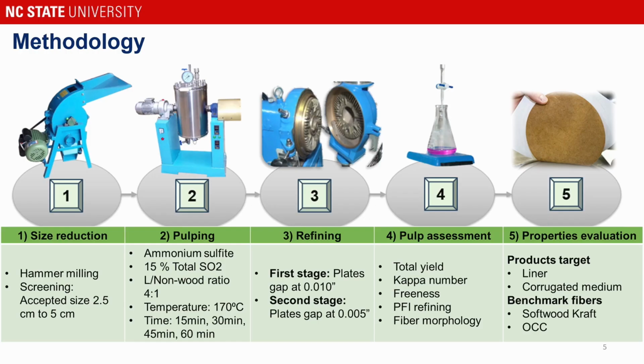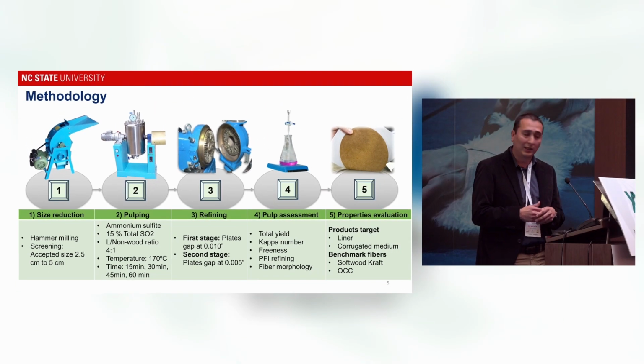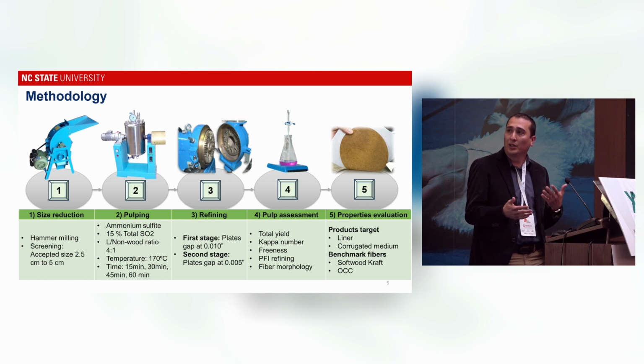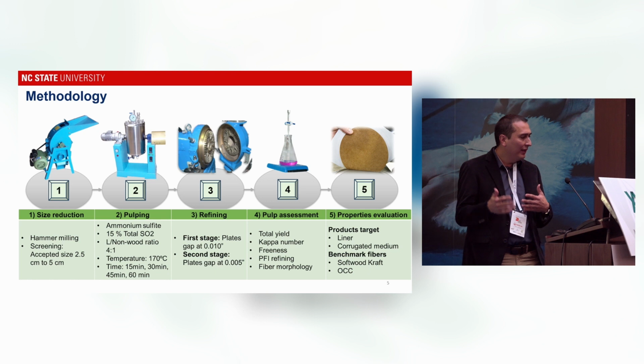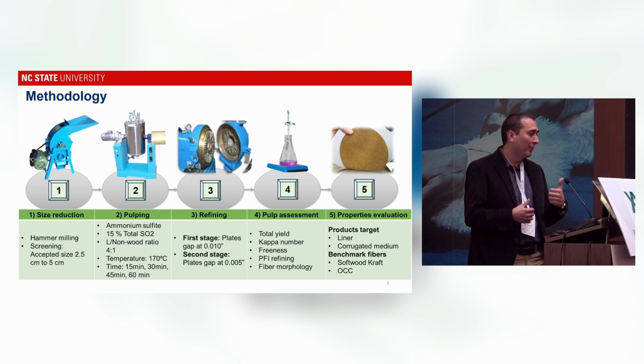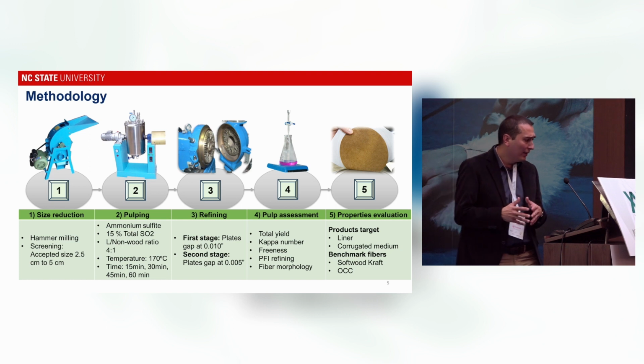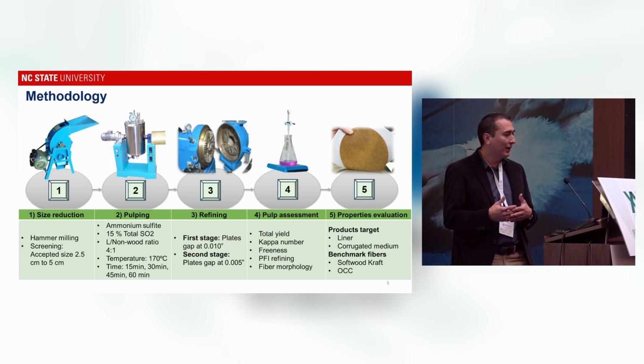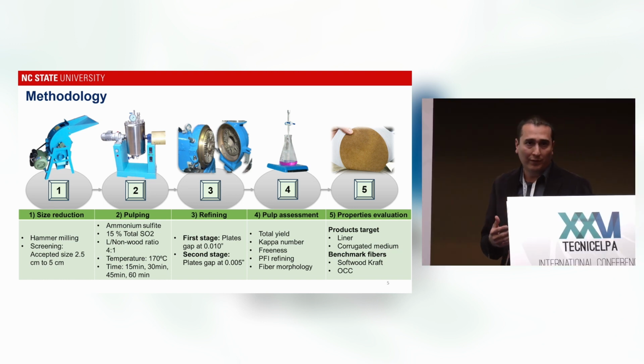So as a methodology that we are using to evaluate this feedstock, we are using a systematic way to test these feedstocks. First of all, we did a pre-treatment of the feedstock. We did some hammer mill and screening. Then we applied different conditions to obtain the fibers, doing a pulping, using a systematic way, using 15% of the total SO2, a liquid to wood ratio around 4 to 1, and using a temperature at 170, which are common process conditions to obtain pulp.